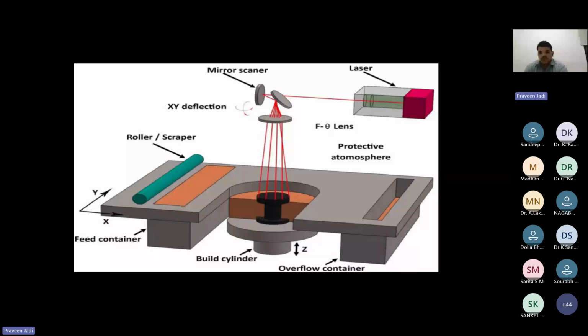Then after 3D printing, we have to remove the unwanted powder. The laser will heat to around 180 to 200 degrees, where we are using a CO2 laser for the polymers. Once 3D printing is completed, we have to wait for the cooling, because the internal chamber temperature will be 180 to 250 degrees. So after 3D printing we have to wait 10 plus hours. If we open it when it is 120 or 150 degrees, there are chances of breakage. So we wait until the chamber temperature is 80 or 90 degrees. Once that temperature is reached, we open and take out the part. We go for sandblasting to improve the surface finish.